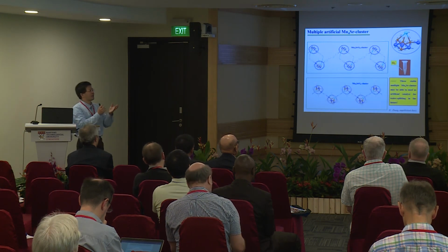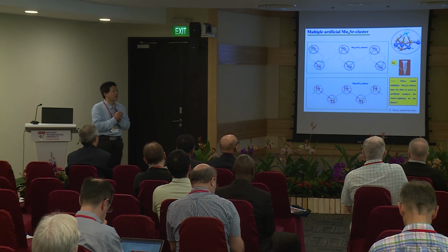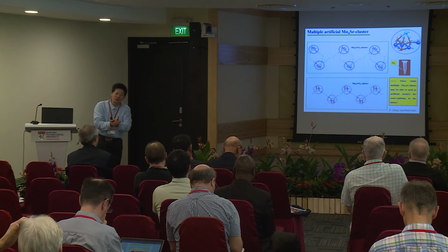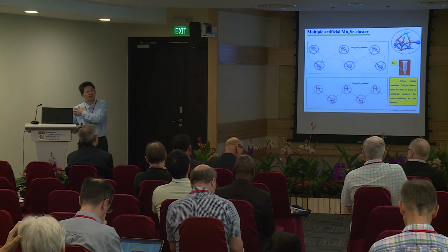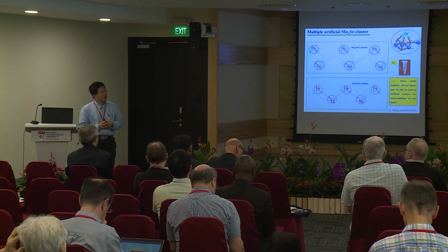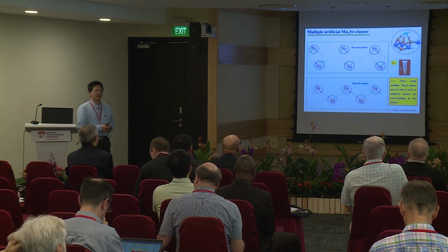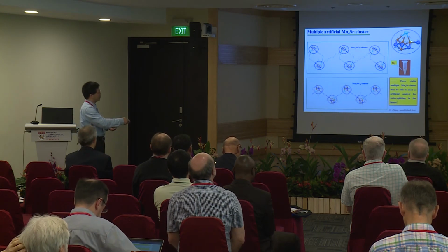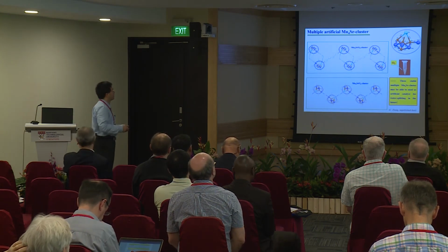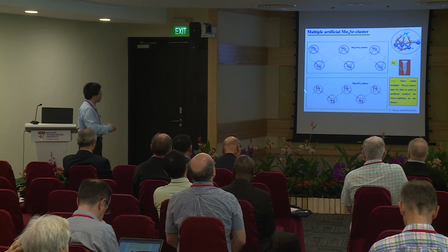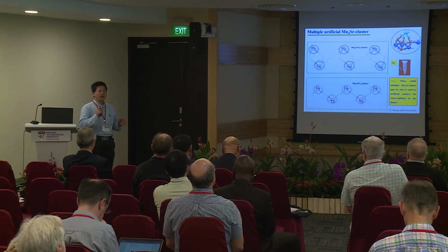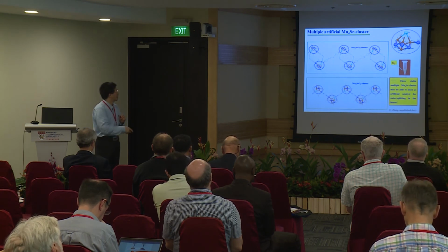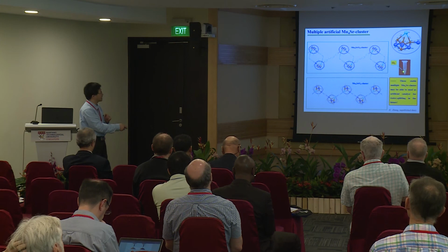Another thing is, okay, it is stable, but we still want to improve it. Because people ask me, can you use your artificial model complex for application in the future? We think probably we can. So we can make supermolecules. Here, we use these units of manganese and strontium, and we can use different ligands. We can get 1D and 2D structures. An important thing is it has become much more stable now, and it's still active for oxygen. You can see oxygen come out immediately.